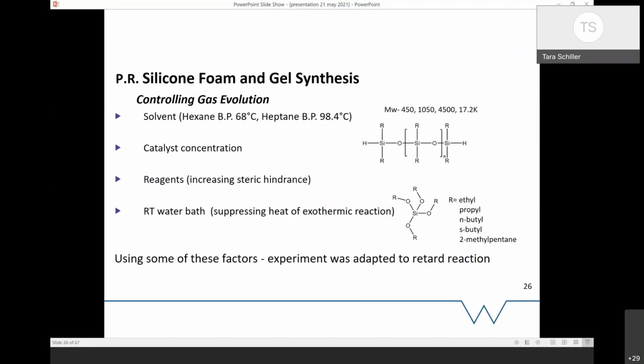And one of the things that we wanted to play around with was the outgassing. So probably should point out here, we can form foams from this. This was the single paper in the literature we got to actually base this work off. And one of the things that we noticed, if we changed the solvent or we varied the catalyst concentration, as I mentioned, the time changes as well. We played around with the reagents, which you can see here, the R group changes from ethyl, propyl, N-butyl, S-butyl and 2-methylpentane. So we've got primary through to tertiary here.